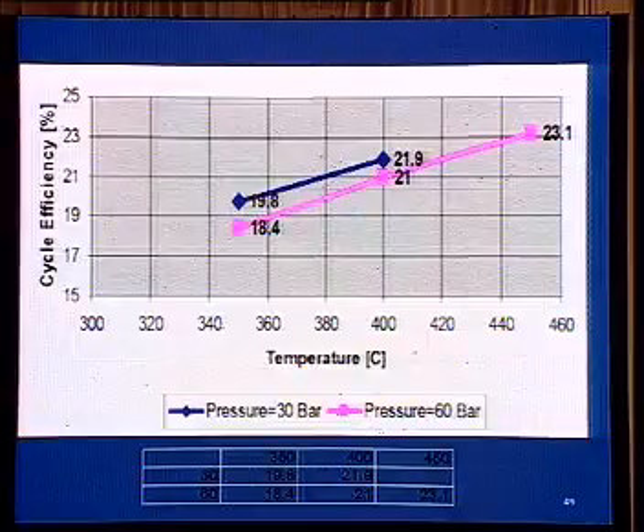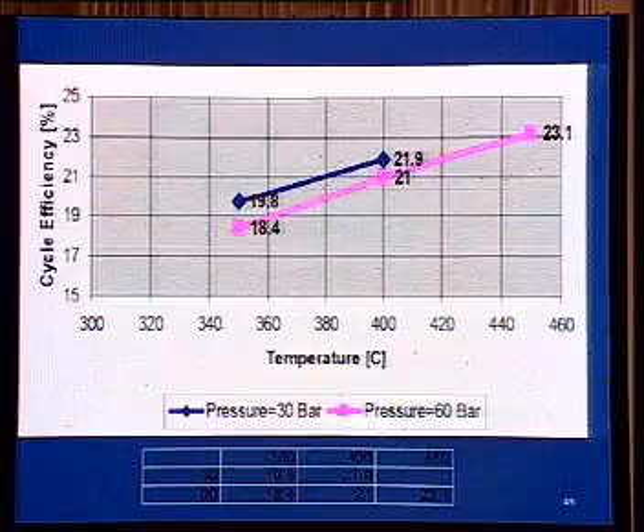One of the issues is, as we looked at the graph previously, as temperature increases, efficiency of the solar plants decreases. But as temperature increases, turbine efficiency increases. So we have to decide at which temperature to operate. If I operate at lower temperature, I will get more energy, but the turbine efficiency will be lower. If I operate at high temperature of say 500 degrees Celsius, turbine efficiencies are good, but then solar efficiencies are lower. So we have to strike a balance and optimize the system. So this is one of the design issues in solar thermal power plants.